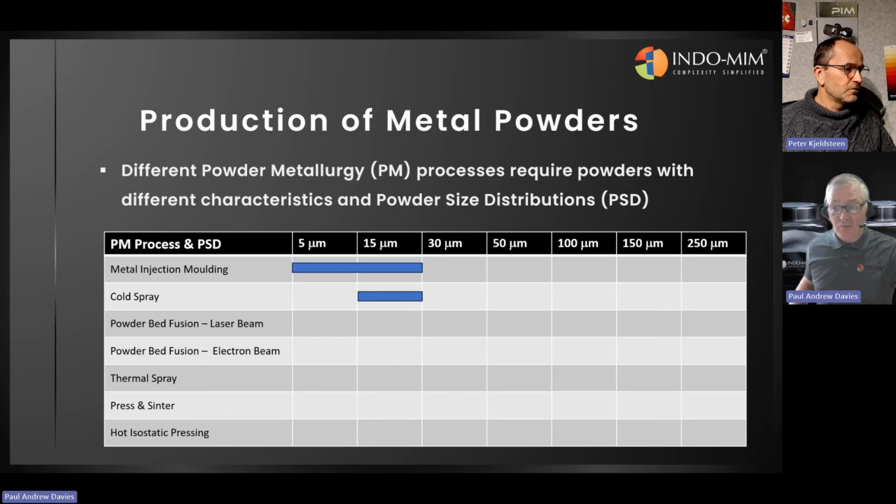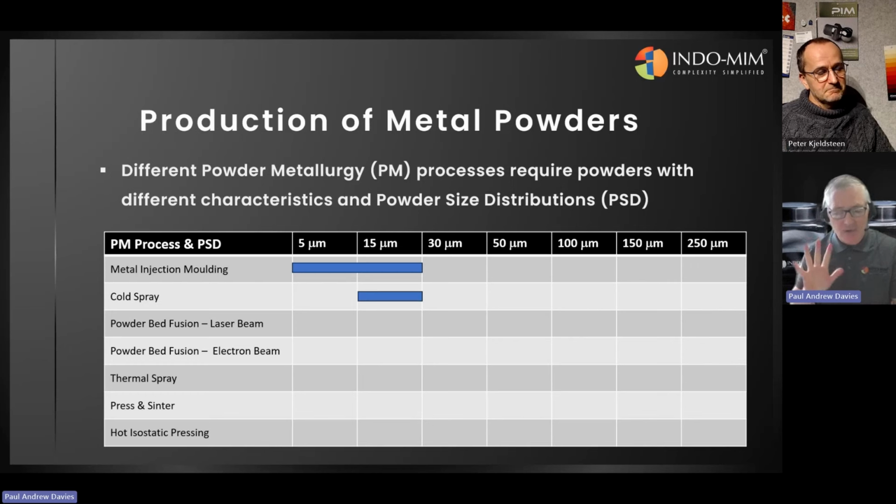And then we get into the additive manufacturing processes. This cold spray. Yeah. I often think the name is misleading because it's not really cold gas, is it? It's not particularly cold. It can be 600-700 degrees C, in fact, yes. And that allows the gas to impart a lot of kinetic energy into the metal powder. So sometimes it's called kinetic spray as well, I suppose. And that high velocity again has a good synergy with gas atomizing, in fact, because they use a converging, diverging, or de-Laval nozzle to make sure it's a very efficient process, and typically limited to relatively soft ductile metals, copper being the most famous, and therefore allowing it to splat onto the surface and form a metallurgical bond. But I guess you could call it cold because it never actually melts the powder.